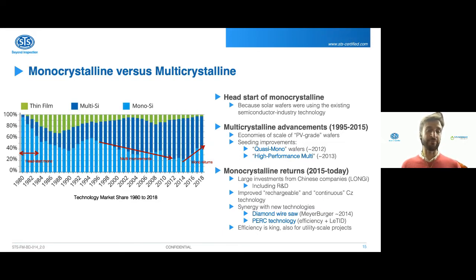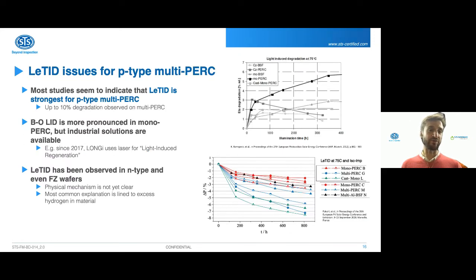In fact, one of the problems that was found with multicrystalline for PERC, it is possible to do a PERC cell on multicrystalline wafers, but you have what is called LeTID, light and elevated temperature induced degradation, and this new degradation mechanism discovered in something like 2012 is actually much more severe on multi. So that is a boost for mono.